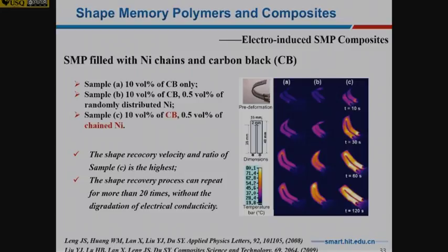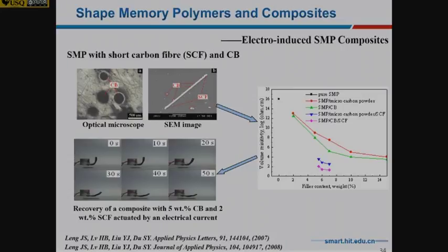So the A, B, C means different columns. A means only carbon black, and B means it has carbon black, but also nickel. But at that time, the nickel is randomly distributed. And C means we have carbon black, and we also have nickel, but the nickel is a chain. So for this one, you can see the color is bright and it's up near 80 degrees Celsius, which shows the better recovery properties.